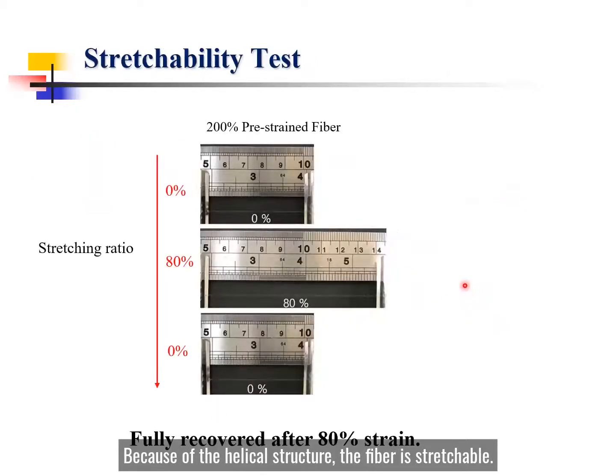Because of the helical structure, the fiber is stretchable. We can see that it fully recovers after 80% strain.